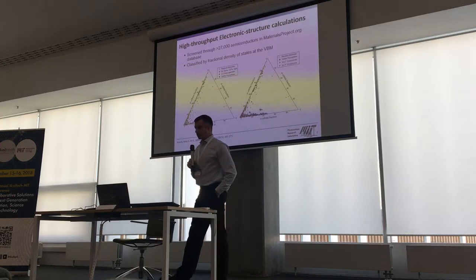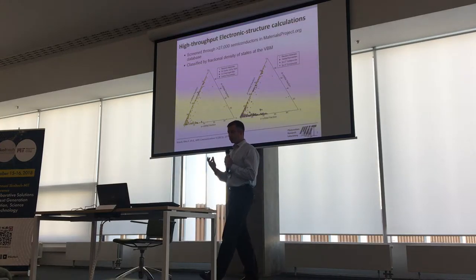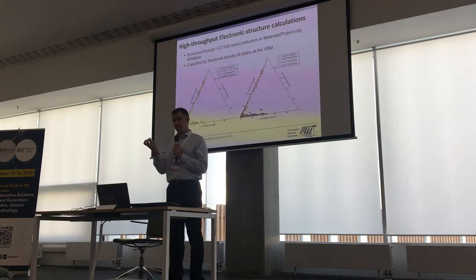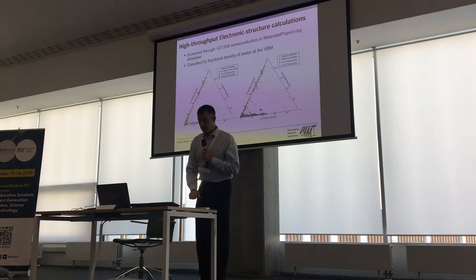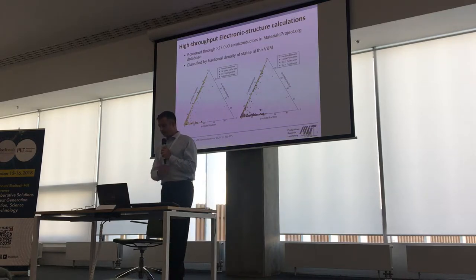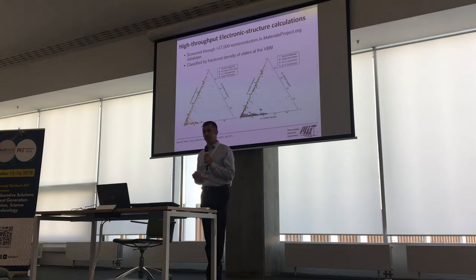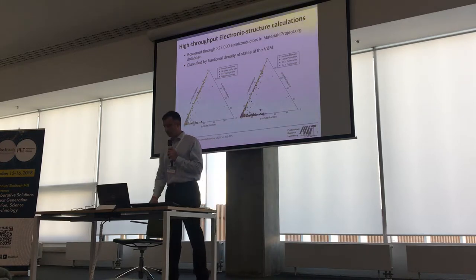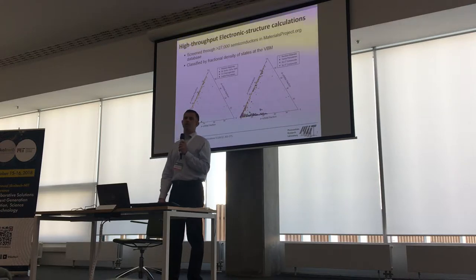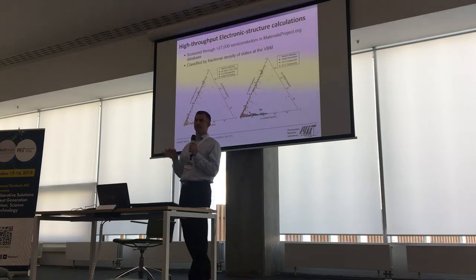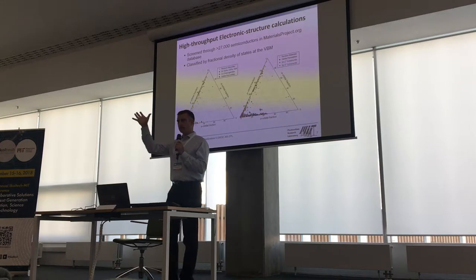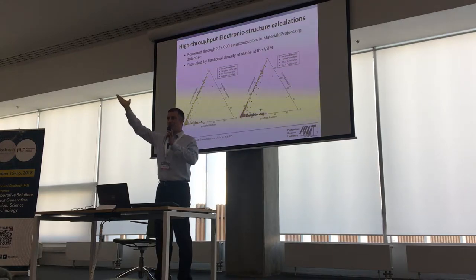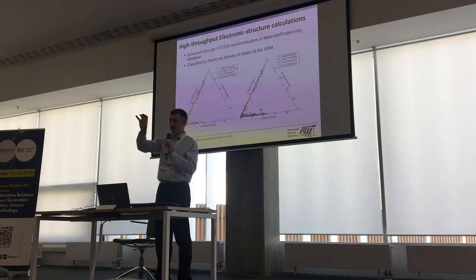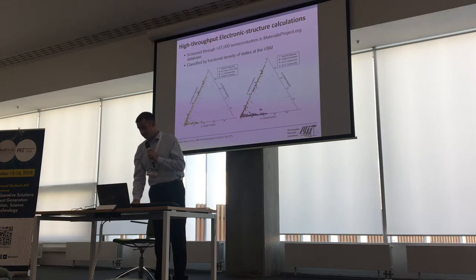And we analyzed the band structures of the perovskite materials, and then used that electronic structure information to screen a materials property database called materialsproject.org, scanning over 27,000 inorganic semiconductor compounds using an API interface with the materials database, and identified a few hundred to thousands of candidate materials that exhibit a similar band structure to the lead halide perovskites, but don't contain lead. So out of that huge subset of materials, we think of it as a funnel, going from 27,000 possible candidates down to a few thousand ones that have the right band structure. Now we begin making them in the laboratory.